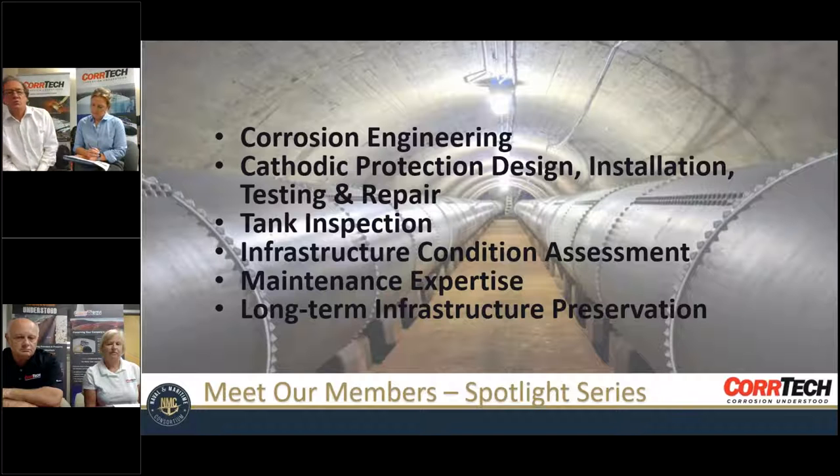Infrastructure condition assessment — a good example is this photograph of pipes about 300 feet long underneath a dam. These pipes were built around 1920; they're riveted steel, internally lined, exterior coated water pipes, four-foot diameter. We see this a lot in the water industry for transmission mains. We evaluate their condition and use statistics to predict pitting, wall thickness loss, and so forth. The key question: how good is it today and how long will it last?